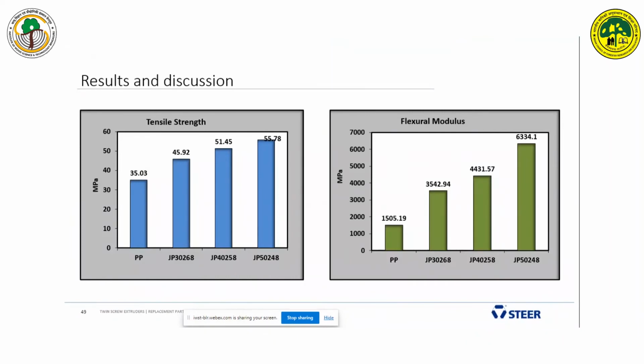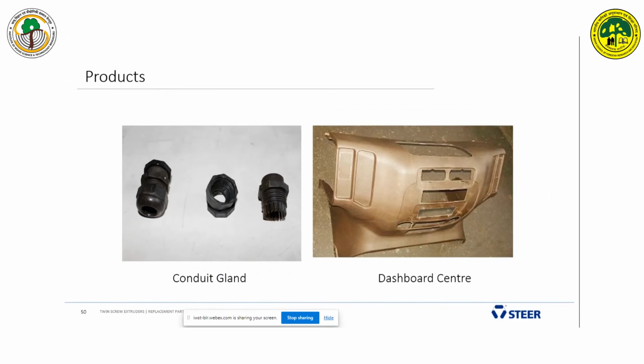If you compare the results and discuss, the polypropylene we use is 35 MPa, and then the increase at 30, 40, and 50%. At 50%, there is a reasonable increase in the mechanical property, tensile strength, and also flexural modulus increases by addition of jute. These are some products we did using jute.